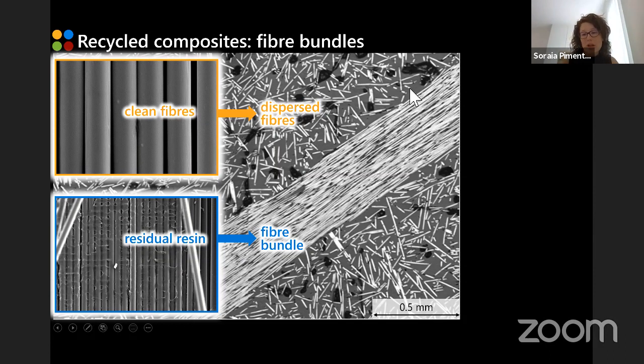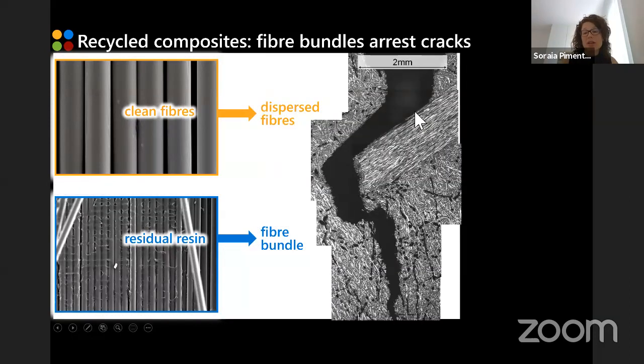Now, when you have a crack propagating in these materials and that crack meets a fiber bundle, basically what the crack needs to do is to go around the bundle because it does not have enough energy to cross it. These bundles also mean that locally you can increase the fiber volume fraction of carbon fibers inside your composite, which also contributes to improve stiffness and potentially strength.